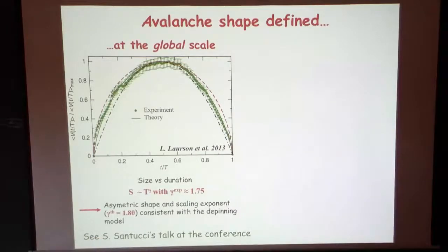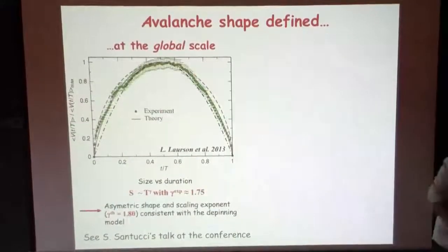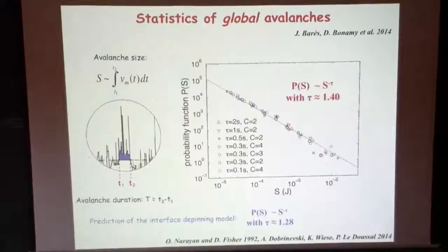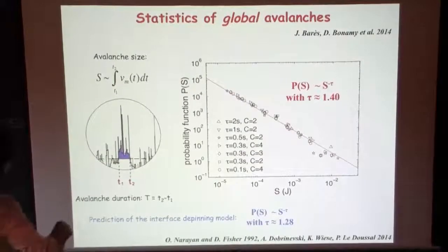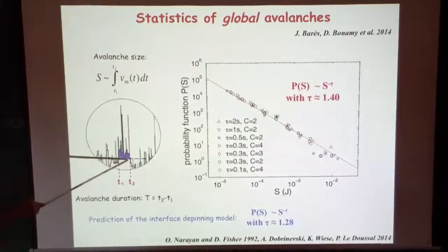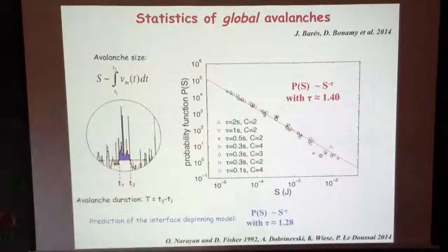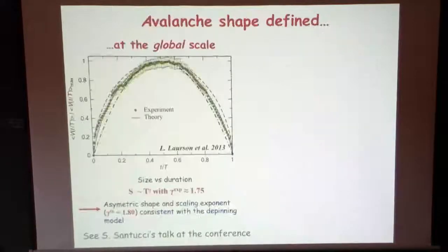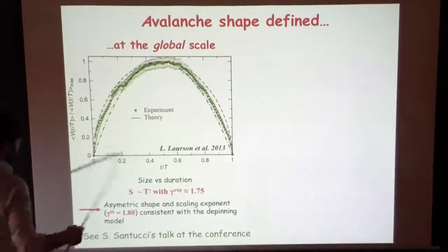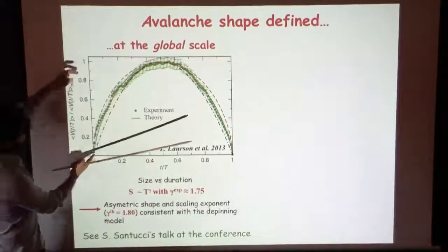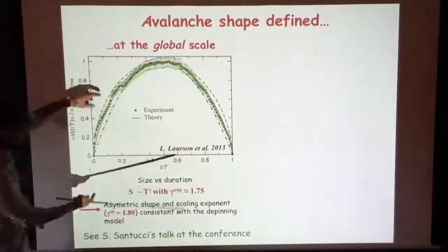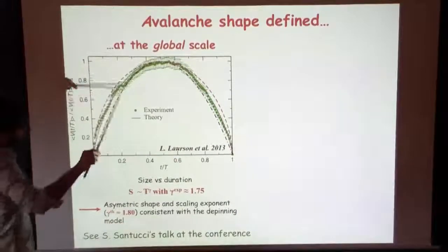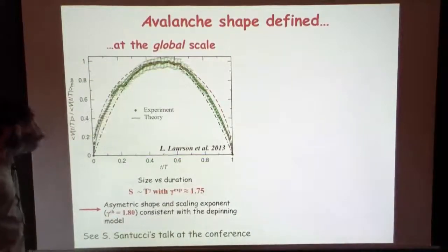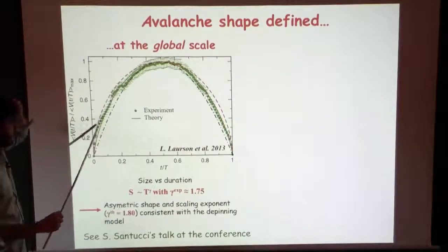But you can now look at, I have a drawing here, the average shape of these avalanches. You average over many of them, and you normalize by their duration, so they all have the same duration. You also normalize their amplitude. So they all collapse on the same curve with a lot of noise, and when you average these avalanches, you find this shape.